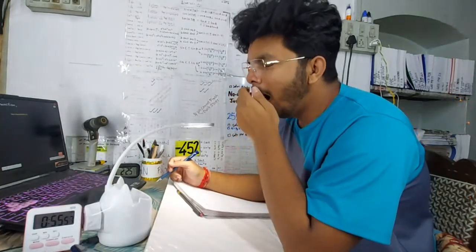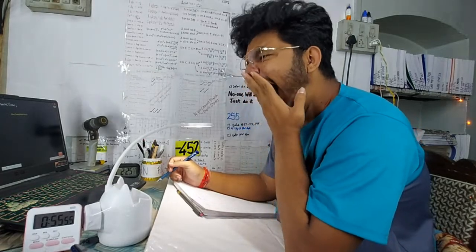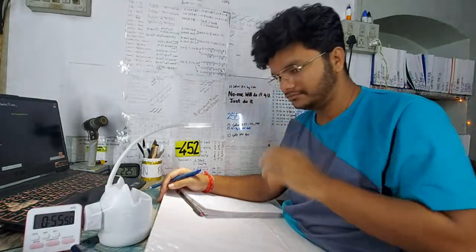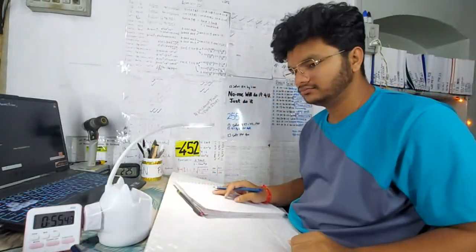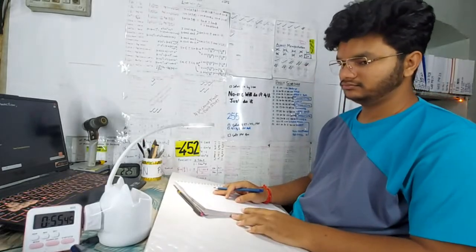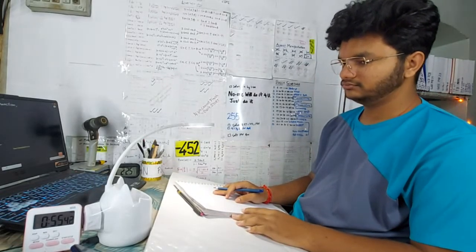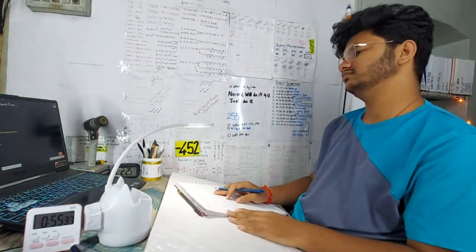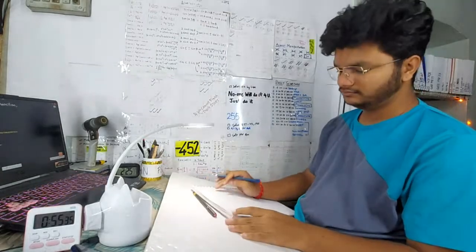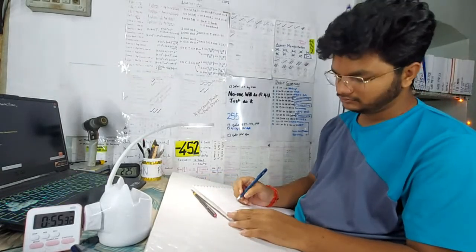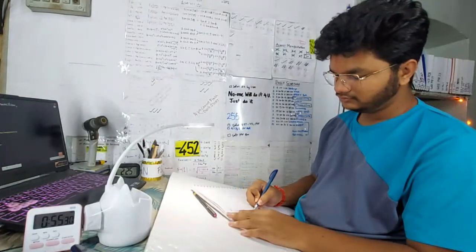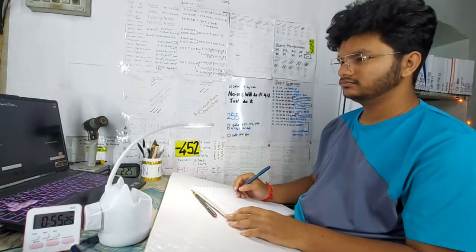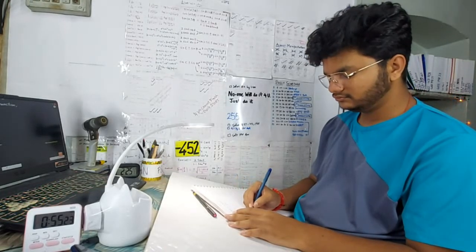Let us see. I try to draw a diagram wherein on y-axis I try to show temperature, and on x-axis I try to show what is called as a rate. Let me say, for example, for this transformation to take place, the reference temperature is A1 temperature. Now, from A1 temperature, as the temperature is decreased, austenite will transform into pearlite. Above A1 temperature, austenite is stable. Below A1 temperature, austenite is unstable. Because it becomes unstable, it undergoes a transformation into pearlite.